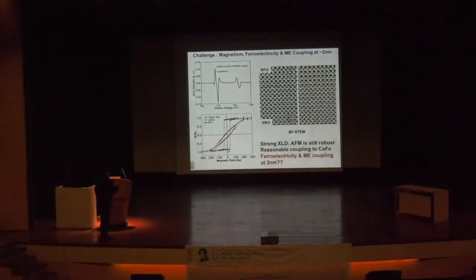Here's the case of 2 nanometers, 5 unit cells of the multiferroic. That's bismuth iron oxide. Is 1, 2, 3, 4, 5. 5 unit cells. Okay. These are atomic resolution images. With these images, you can not only get the atomic positions, you can also get the relative displacements. And what you can see from this is that this is the strontium ruthenate layer, this is a metal, is that the dipoles in the bismuth iron oxide are all pointing towards the bottom electrode, which is exactly what it should do. But it also says that there is nowhere in the sample where the dipoles are pointing up.